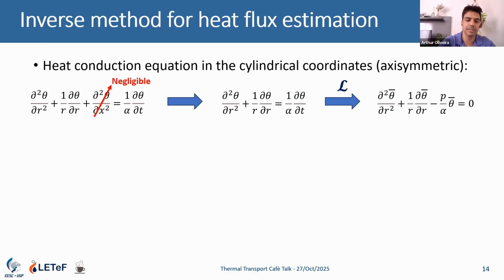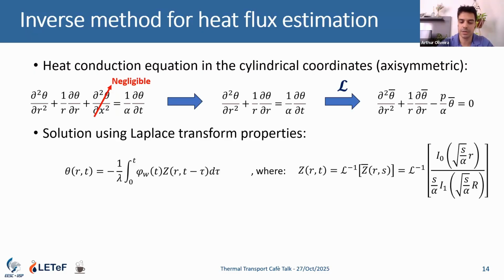So we have a 1D transient problem that can be solved, for example, using Laplace transform. I'm not going into the details of the math, just showing the procedure. We have the solution in Laplace space as a convolution. We solve the inverse Laplace transform using an algorithm - you can use any, for example Stehfest. We used Valko and Abate because it's very stable and easy to implement.